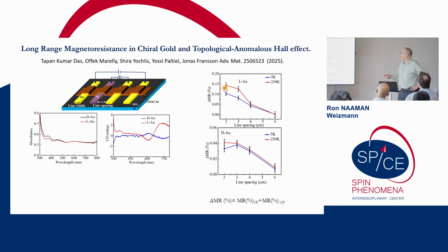Okay, so what we find here is that for this structure, we can get a magnetic resistance up to about 4.5 micron. So it's really a long-range spin transport at room temperature. The explanation for this is that there is, of course, spin randomization, but also spin polarization creation during the motion.